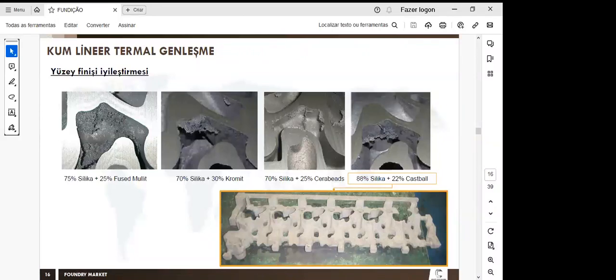We can see the casting finish surface of a cylinder head. This area is the water jacket. And 22% of Castball can provide a similar casting finish to 25% mullite sand, 30% of chromite, or 25% of a fused mullite. In this real case in cylinder heads, we can see the difference in the results. Castball provides a very good surface finish, very comparable with the other types of ceramic or natural sands with low thermal expansion.